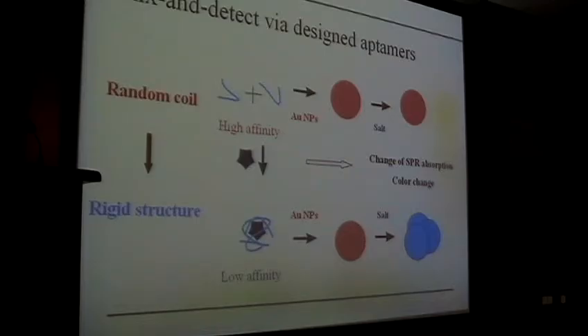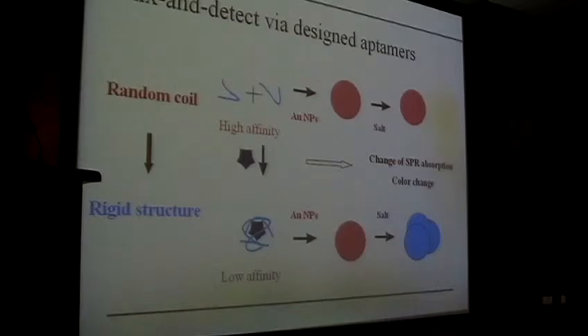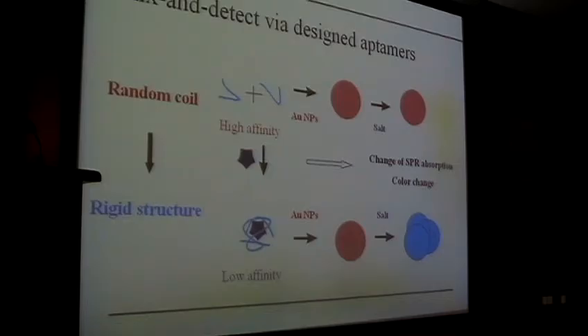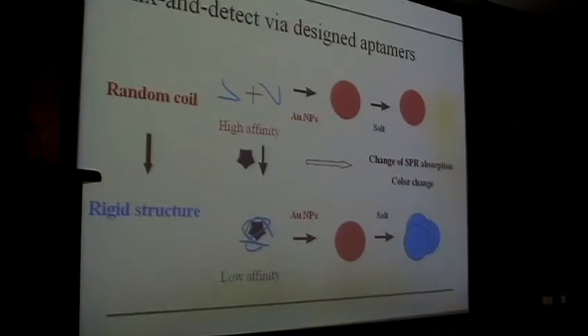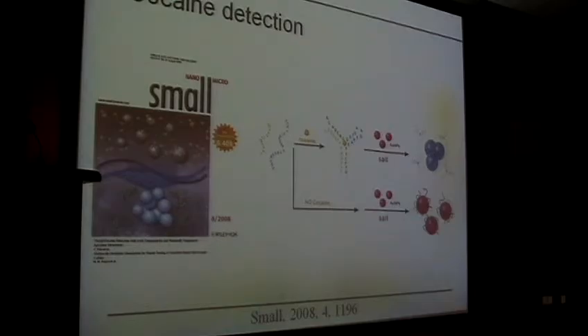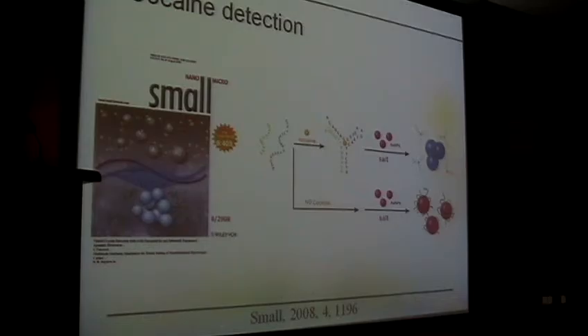To achieve faster kinetics, we engineered the aptamer by cutting it into two pieces. We expect that the target will assemble these two segments into the intact structure. These two short segments can bind to the gold nanoparticles when free, protecting them from aggregation — the solution is red. But once the target is present, the intact structure forms, cannot bind, and the color turns blue. Indeed, with the cocaine aptamer cut into two pieces, in the absence of cocaine it is red, and in the presence of cocaine it forms the structure and turns blue.